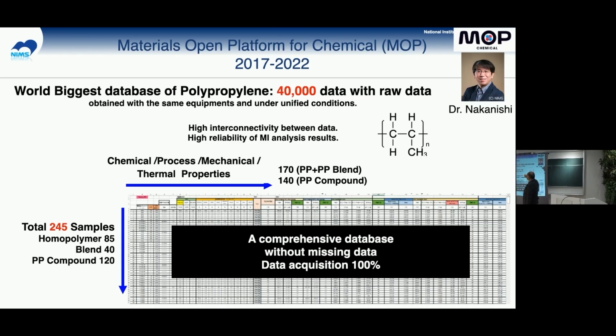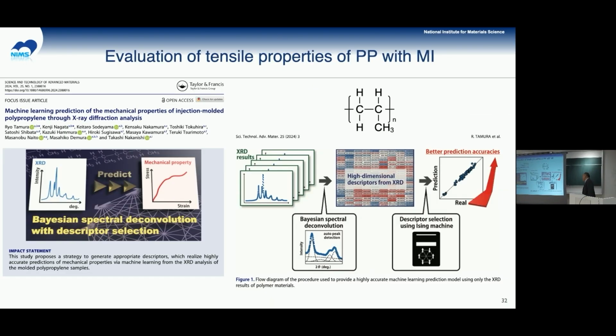As the target molecule, we focused on just polypropylene, as shown before. We performed many experiments, like mechanical properties, thermal properties, chemical properties, whatever. At the end we got more than 40,000 data points. I think that is the largest database of commercially available polypropylene. These are precious data, because we performed every experiment with the same apparatus and instruments, the same person, the same method, everything the same. So we got very pure data, more than 40,000 data points.